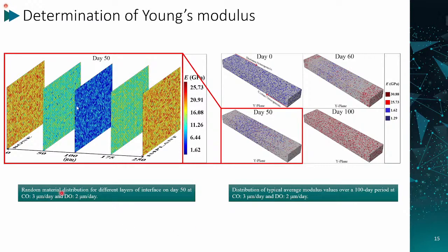These two figures show the random material distribution for different layers of the interface on day 50. We can see on day 0, all the lowest values of Young's modulus are randomly distributed in this model. And on day 50, some highest Young's modulus appears at the two ends and also in the middle at the seal and deal front. So for this day 50 model, we just show several cross-section layers. Even in each layer, the Young's modulus material properties are randomly distributed. But on average, along the length of this model, the two ends have the higher value, and where the seal and deal meet at this middle point, it still has the lowest value of Young's modulus.